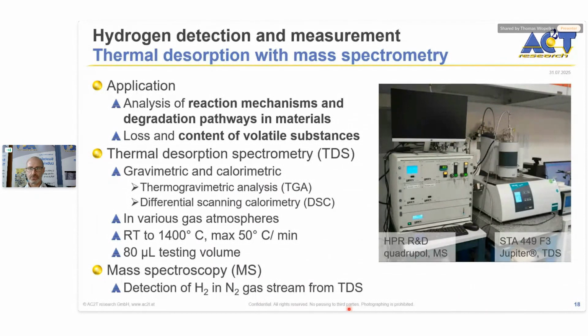And simultaneously, you can do some differential scanning calorimetry, where you measure the heat flux towards or through the sample during the heating process. And these two signals allow you to determine the reaction mechanisms or phase transitions in the material you investigate, if you have a good knowledge of the material yourself. Without knowing anything about the material you investigate, it will not be possible. And we also equipped this TDS system with a mass spectrometer. And with the mass spectrometer, we can detect, for example, the outgassing of hydrogen of samples that have been stored previously to the investigation in TDS in hydrogen with high pressure.